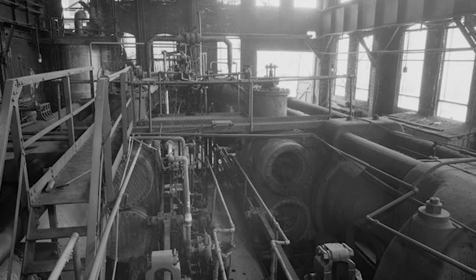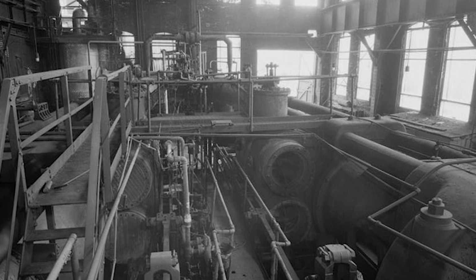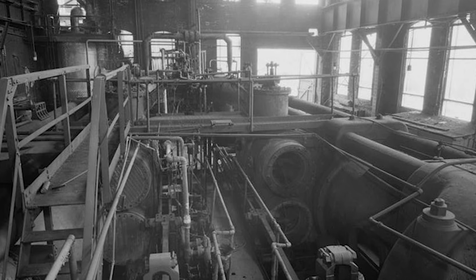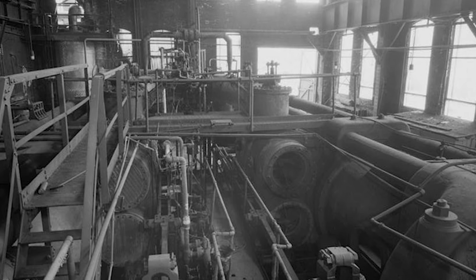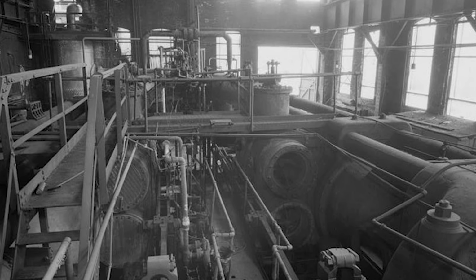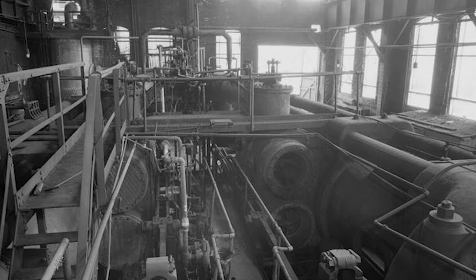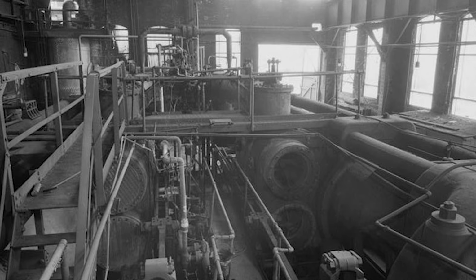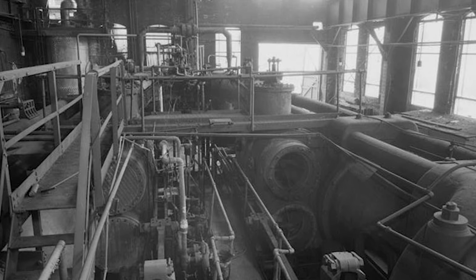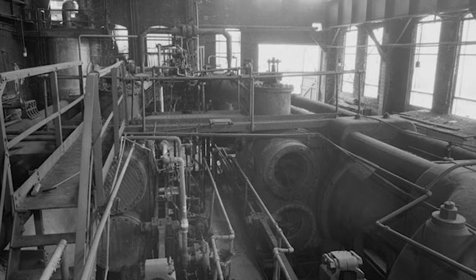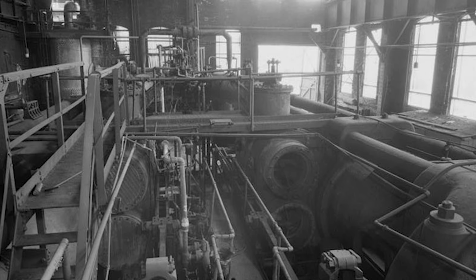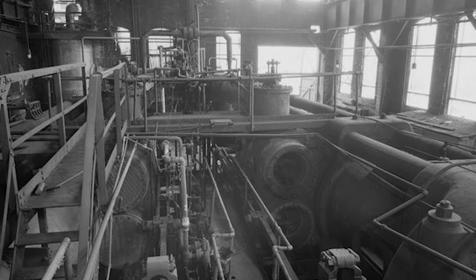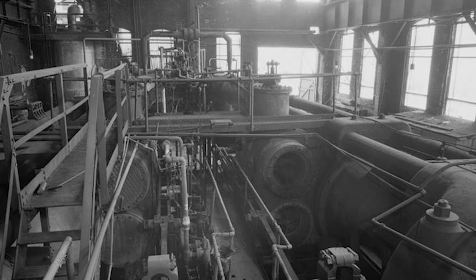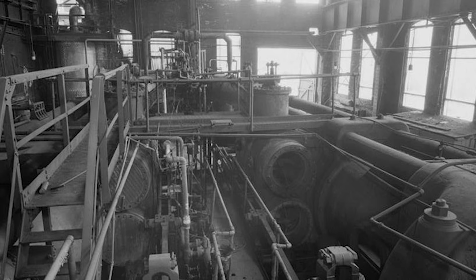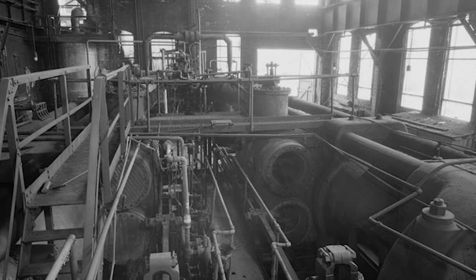Pressure tests conducted during routine maintenance showed that the shells could safely handle 150 pounds per square inch, 25% above their rated capacity, while maintaining the structural margins that had been built into the original design. The thick walls that had been criticized as wasteful over-engineering were proving their value as insurance against the unpredictable stresses of continuous industrial service.